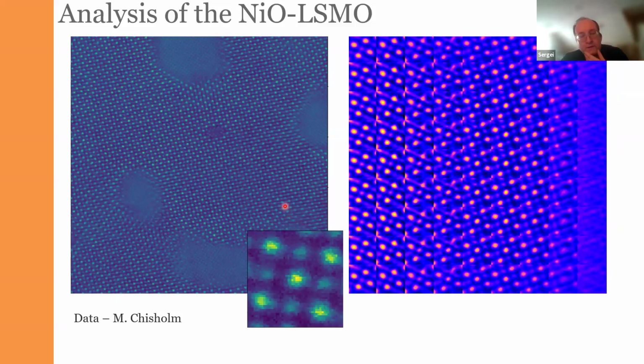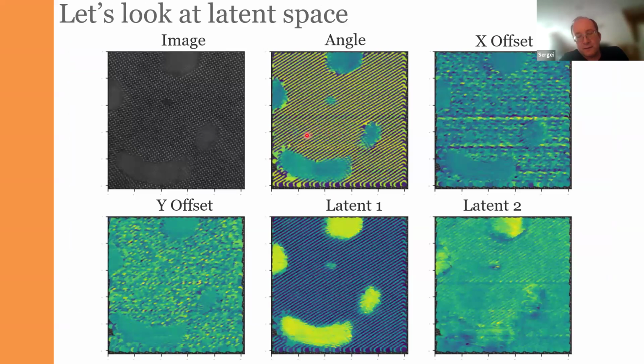So we can, of course, look at the evolution of what the latent variables mean by using the latent representation. In this case, it's very clear that it represents the A lattice and B sublattice. We can play with the angle distributions to get a better idea of that. Or we can try to reproduce this analysis on a different image from the same series. And again, you can see that there is some factor of variability inside the nickel oxide layers. So definitely it tells us something interesting.